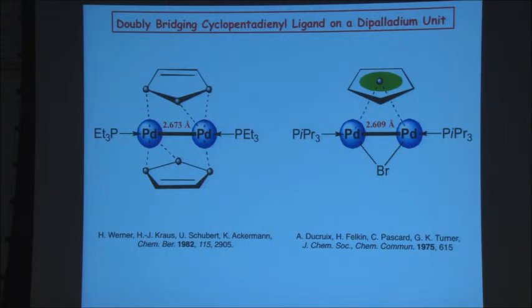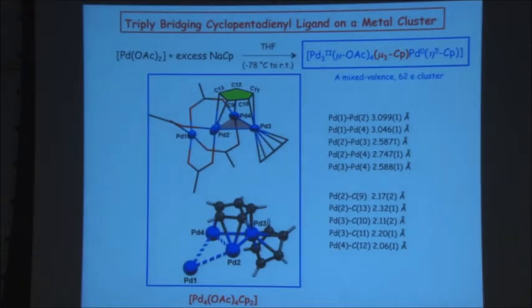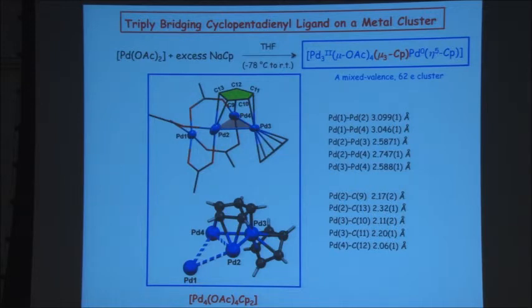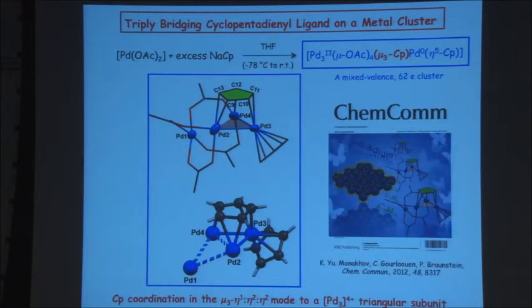of Cp interacting with 3 metal centers until, fortunately, a good postdoc in my group was able to produce, I should confess it was not designed, a palladium cluster in which, I won't go into the detail, one face of the palladium butterfly is capped with a triply bridging cyclopentadienyl ligand. So now we have a mixed valence cluster which displays this interesting structural feature, the first Cp minus ligand to interact with surfaces. So that expands the scope of the metal cluster surface analogy which I mentioned earlier on, and there is a lot of scope in that people can reinvestigate in more detail.